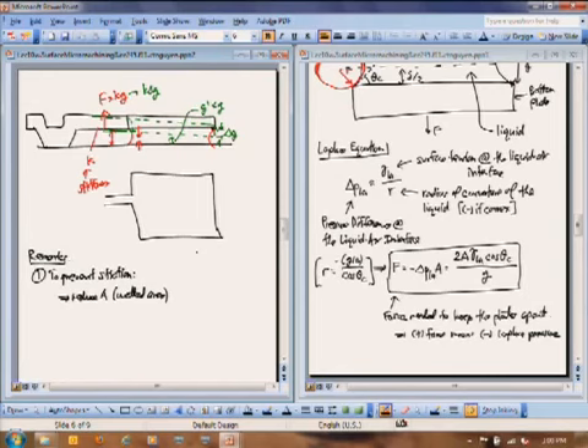What's the problem here? They could fab devices, and a certain percentage of them would go unstuck, but a lot of them were stuck initially. And even after you release them and they weren't stuck initially, if moisture condensed on the thing, if you didn't have a good enough package and it created liquid between the plate and the substrate, down it goes. So not only did devices fail immediately after fabrication, but even during operation there was a possibility that they could fail. So it's these types of things that take a long time for these products.